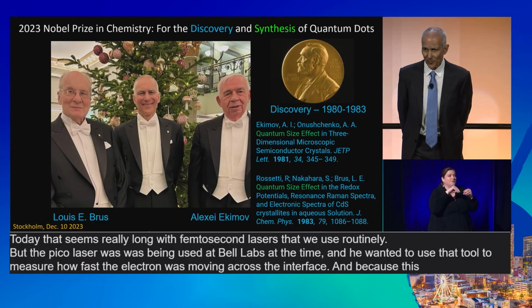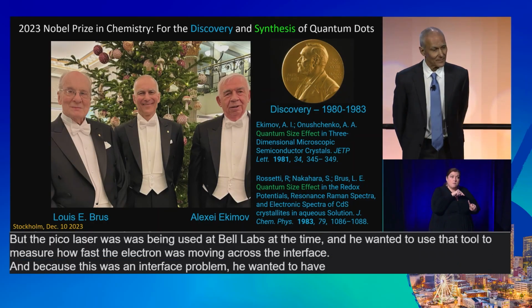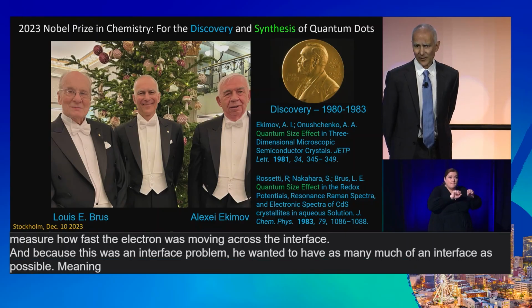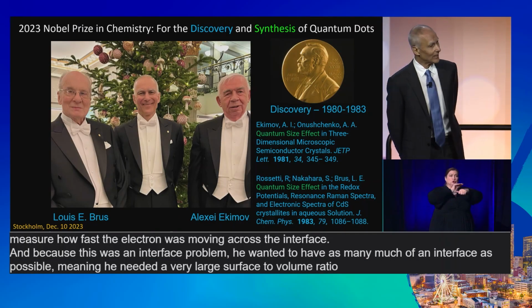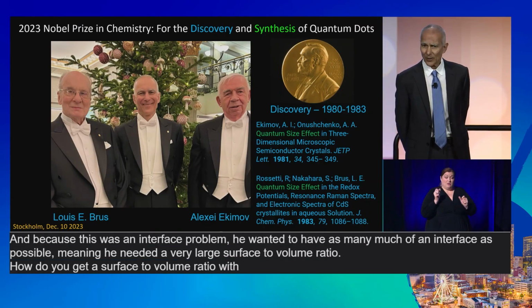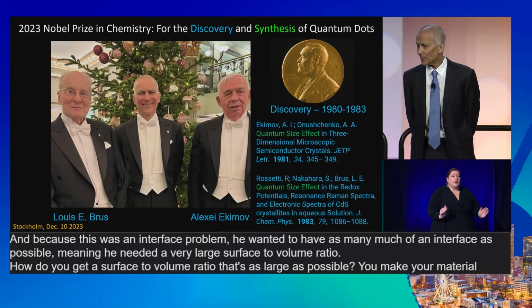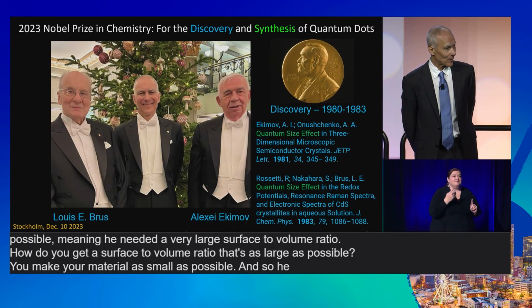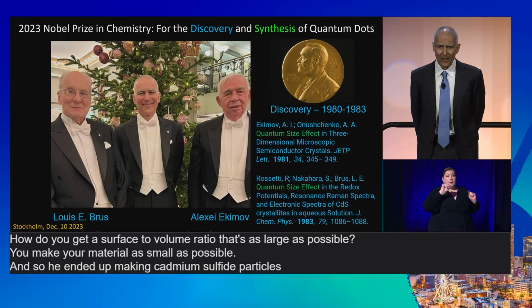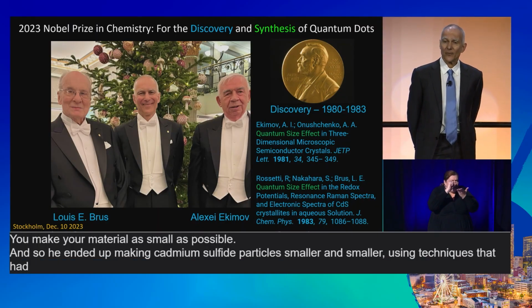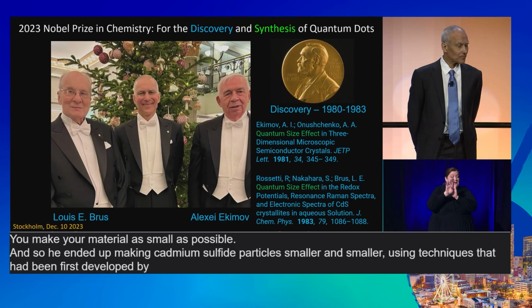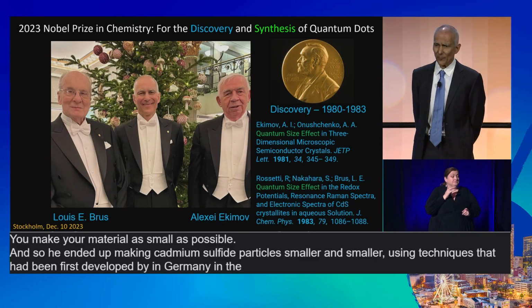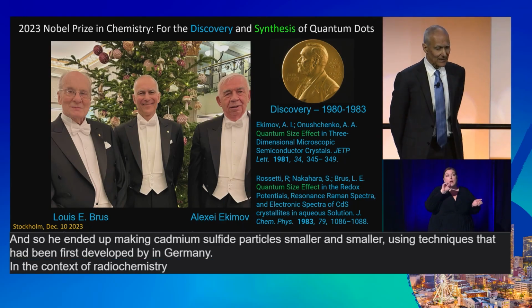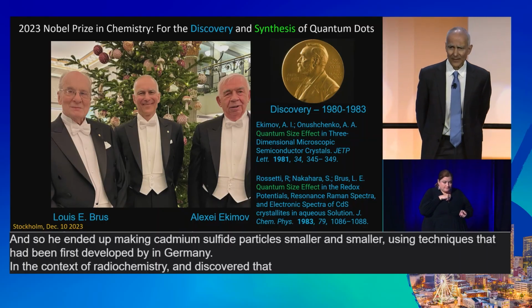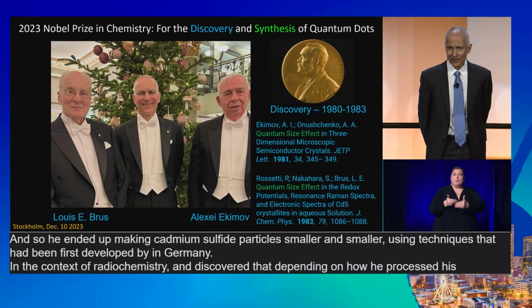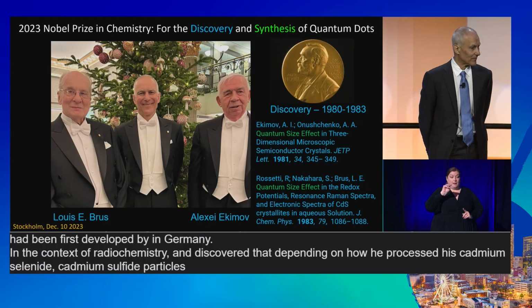And because this was an interface problem, he wanted to have as much of an interface as possible, meaning he needed a very large surface to volume ratio. How do you get a surface to volume ratio that's as large as possible? You make your material as small as possible. And so he ended up making cadmium sulfide particles smaller and smaller, using techniques that had been first developed in Germany in the context of radiochemistry, and discovered that depending on how he processed his cadmium sulfide particles, he also would get different colors.